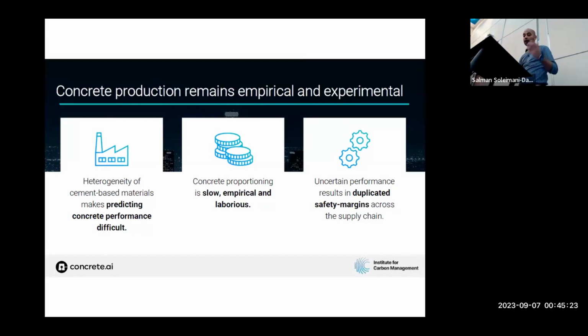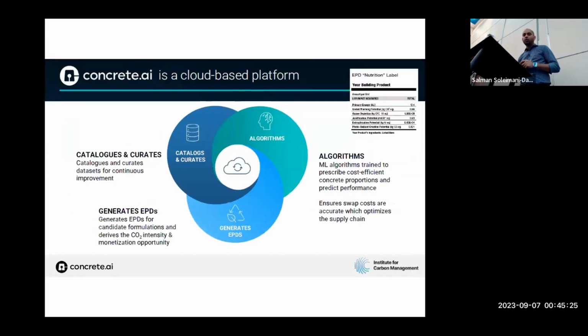Now I can tell you, and I'll tell you this on the basis of data, we went out and curated data from all around the world. So we got data from India, we got data from Canada, we got data from the US, we got data from Europe. In general, concrete produced all around the world is over-designed by a factor between 20% and 200%. These numbers are actually real, and the range is in fact enormous. It's almost hard to believe, but the numbers are really, really wide. You can argue that there's on average at least 30 to 40% over-design on a typical concrete that's produced.